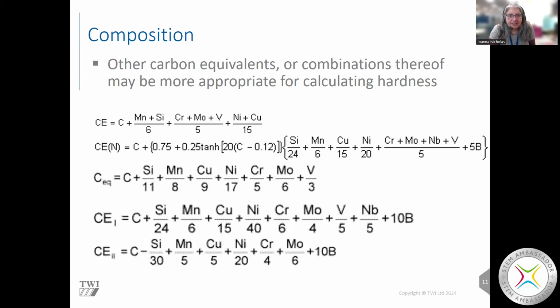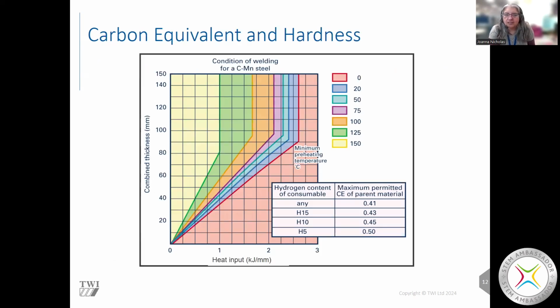There are lots. So here are 5 different carbon equivalents. The IIW carbon equivalent at the top there with the addition of a silicon term. Then we've got complicated CEN, and then some other carbon equivalents that are used. All of them are doing the same sort of job. They're a shortcut for composition. We're trying to define what the composition is, and we use a carbon equivalent to work that out. Now, in the 1960s, there was quite a lot of work done at TWI, which managed to show a relationship between carbon equivalent and hardness, and we can make use of that to help estimate whether we're going to get a problem with fabrication hydrogen cracking or not.